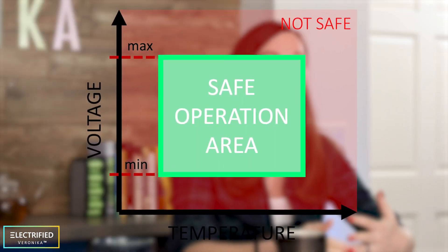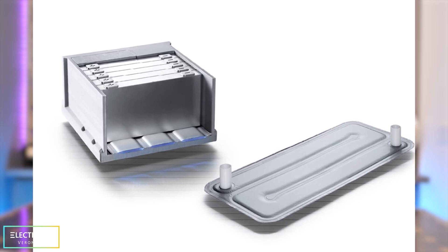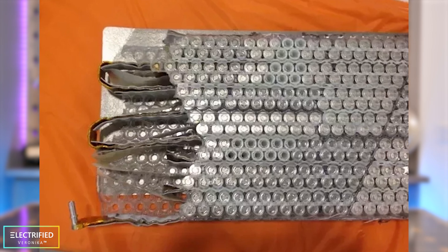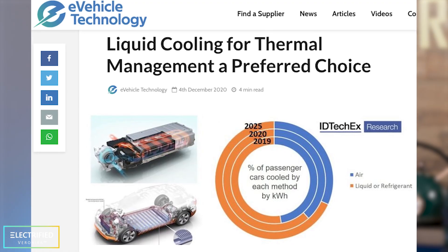As we all know, batteries have a comfortable temperature window — they don't want to be too hot, they don't want to be too cold. So you have to warm them up when it's freezing outside and cool them down when you're doing fast charging or when it's just too hot. In passenger cars, the most common approach today is an active liquid cooling system with fluid running through a cooling plate, with cells on top of the plate. Tesla, for example, uses tubes where coolant flows through with a contact area to the cells. Air-cooled systems are not very common anymore — the Nissan LEAF was well known for air cooling, but those batteries degraded over the years, and many people want to replace them with newer water-cooled LEAF batteries because they have a much longer life.